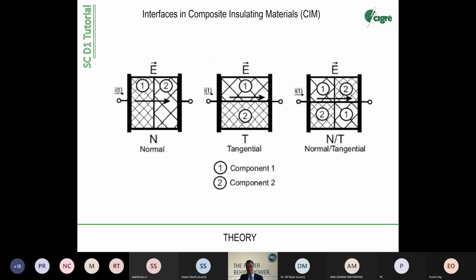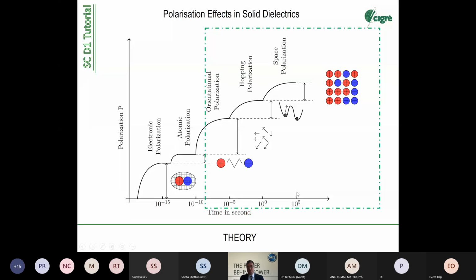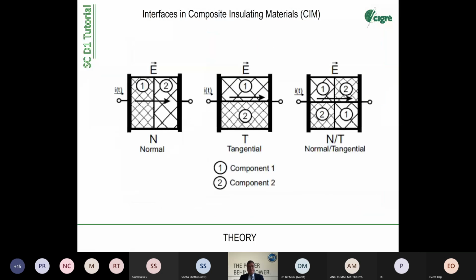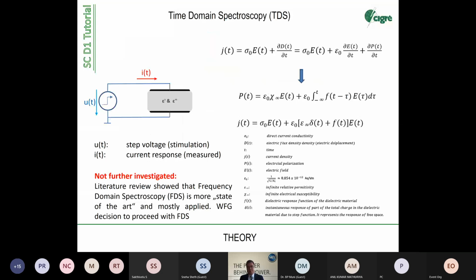So, and what we also can see here, we have to look at long times. Long times means low frequencies. So after reviewing the available procedures and methods, we found very nice methods coming mostly from universities and from scientists, which are called time domain spectroscopy, TDS. It's a very interesting way to analyze materials. It's given here on the left side a very simple scheme. So you have a stimulation. It's normally a step voltage, and the step voltage has a response which is called current response, and this current response is given by the quality and nature of the dielectric.